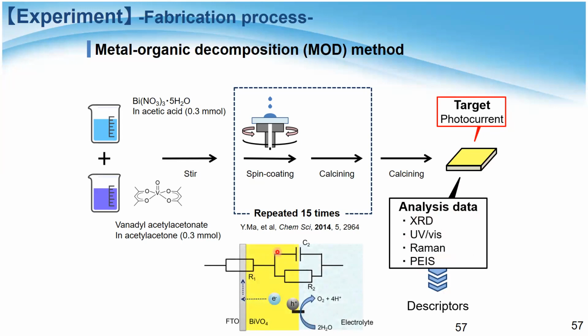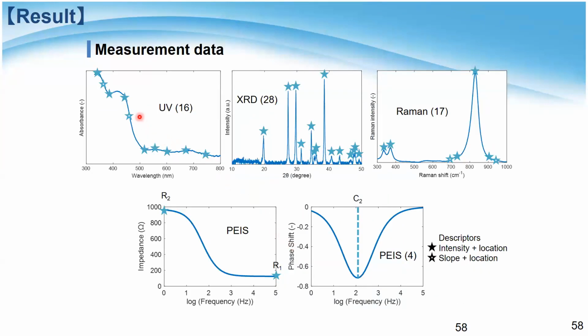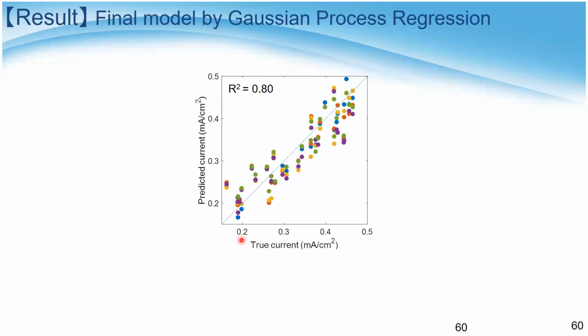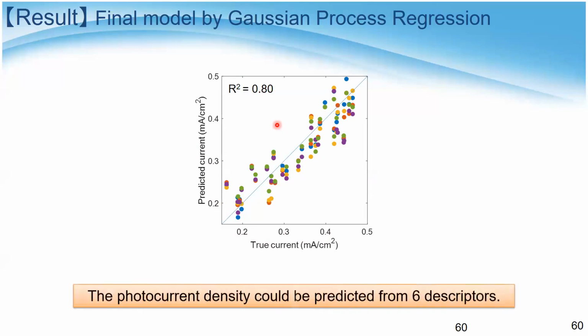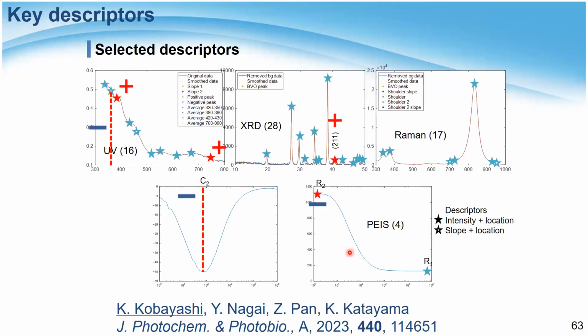And again, we use PEIS for the photoelectrochemical properties. And here are the descriptors we selected in the UV-Vis, XRD, Raman, and then PEIS. And we could successfully, again, predict photocurrent nicely using the experimental data, about 50 samples, and our R2 value was 0.8, which is quite high, thinking about this function was prepared by the experimental data. So photocurrent density could be predicted from the 6 descriptors in this case, and they are the 6 descriptors we selected.